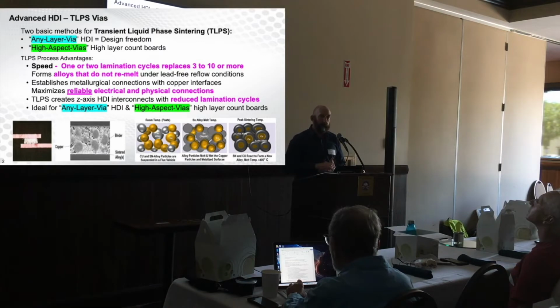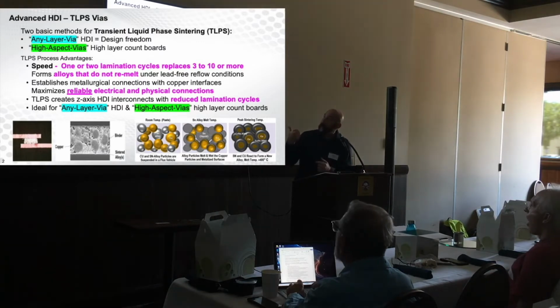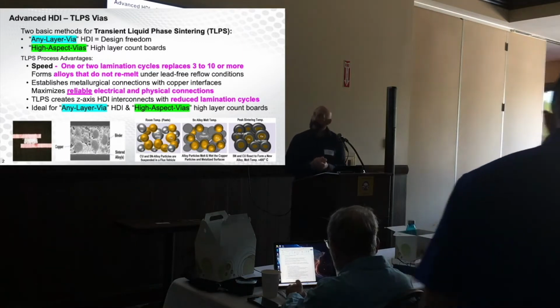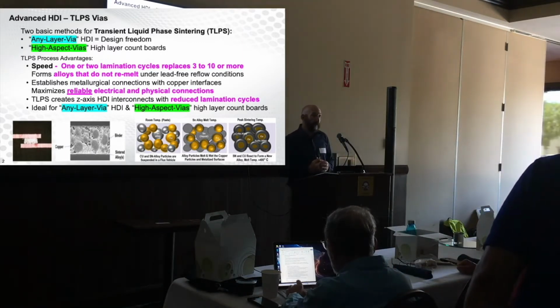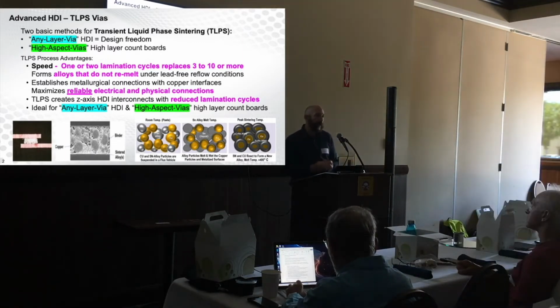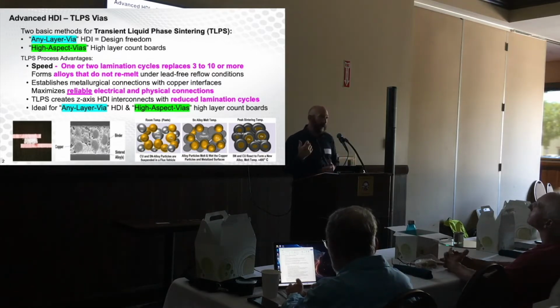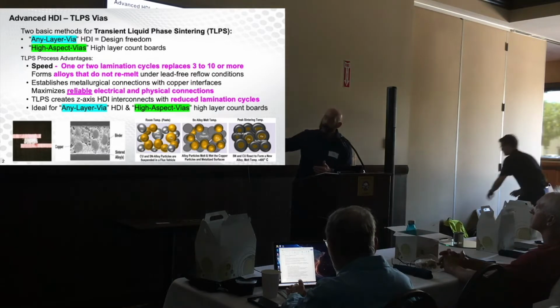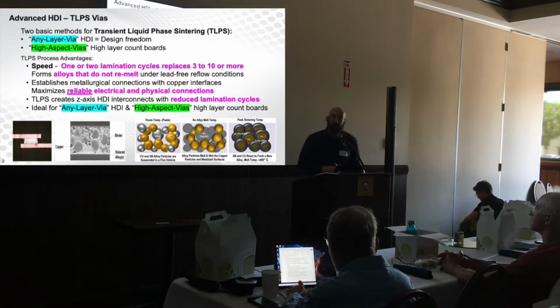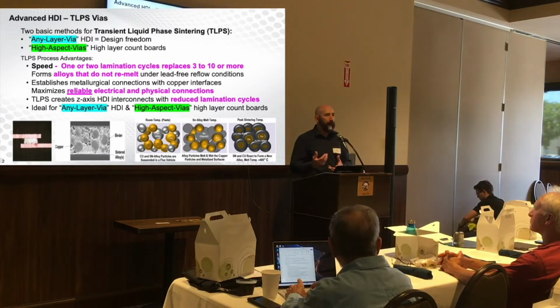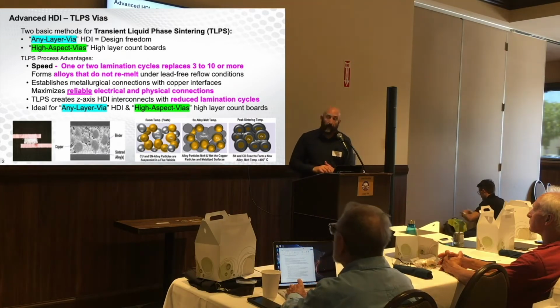So, for those who are not familiar with Ormet, basically it's a non-reversible solder. It takes advantage of the fact that copper and tin form alloys at relatively low temperatures, and the resultant alloy has a much higher melting point. So it's a kind of solder that won't melt. The other advantage is it bonds to not only the copper particles within the paste, but also the copper interlayers. So you form an intermetallic bond with your copper interlayers.